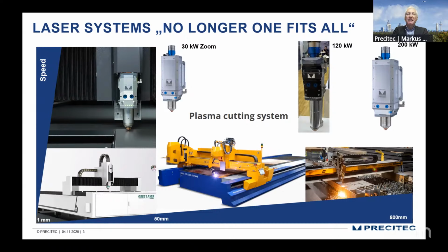And you see that the numbers, the kilowatts which you see at the cutting heads, are increasing and increasing and increasing. And I myself, I'm with Precitec for 30 years, more or less. And actually, I would say 12, 13 years ago, there have been discussions on the thermal focus shift in processing optics already at 4, 5, 6 kilowatts laser power. And now we're talking about 200 kilowatts. And we are still talking about transmissive optics.